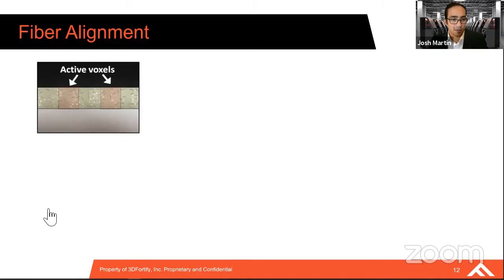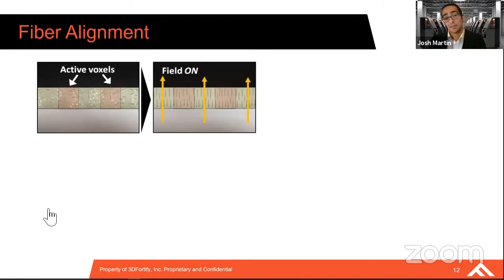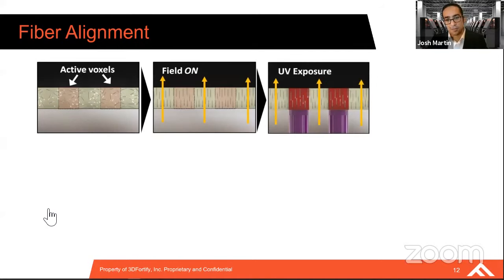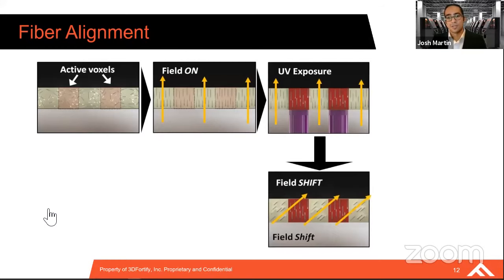Now, the way that this is applied during our additive manufacturing process is that the continuous kinetic mixing system mixes these treated fibers within a resin. Those fibers are then oriented with an onboard magnetic system, essentially surrounding the build area in the systems that you can see behind me. UV light is then used to selectively cure particular voxels, effectively programming the alignment in those regions and leaving the adjacent regions to be essentially reprogrammed.